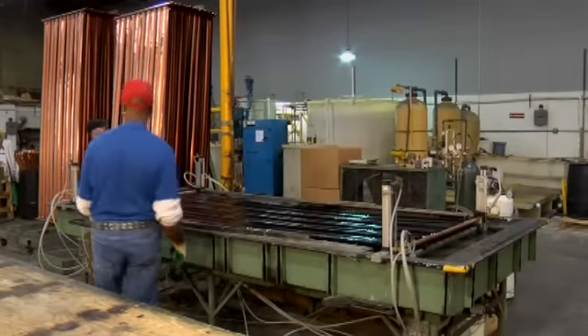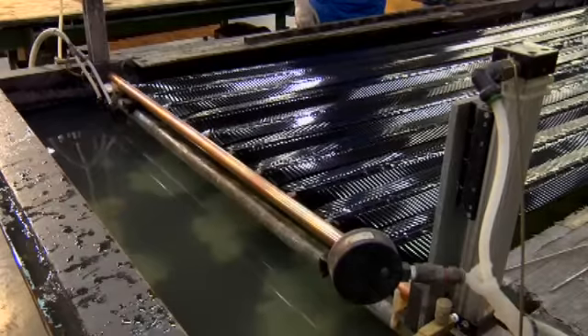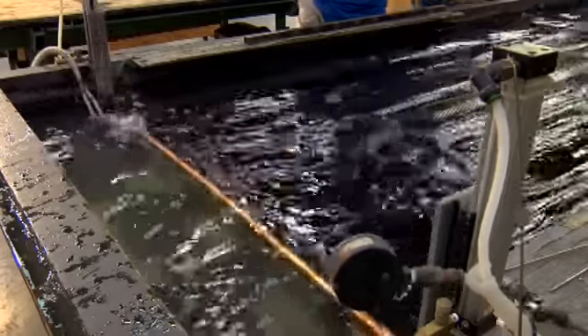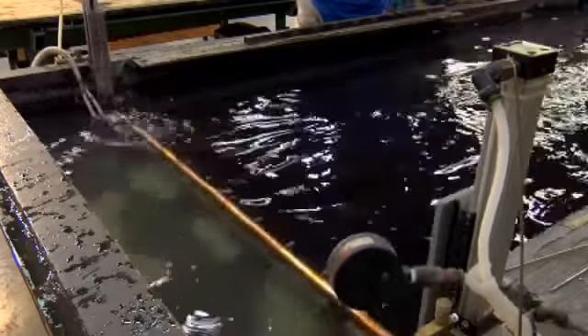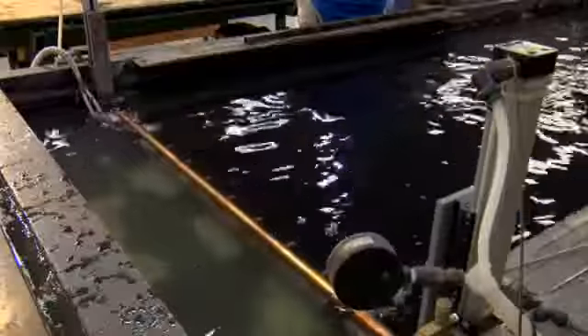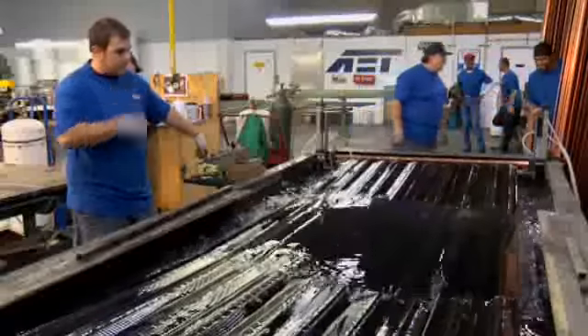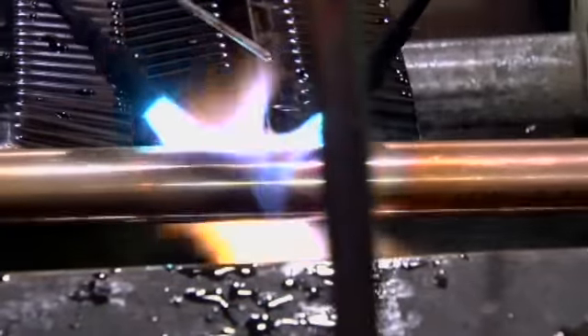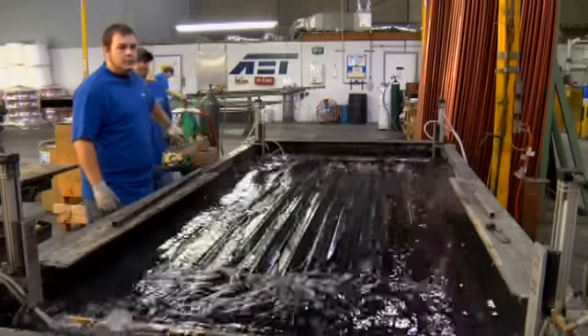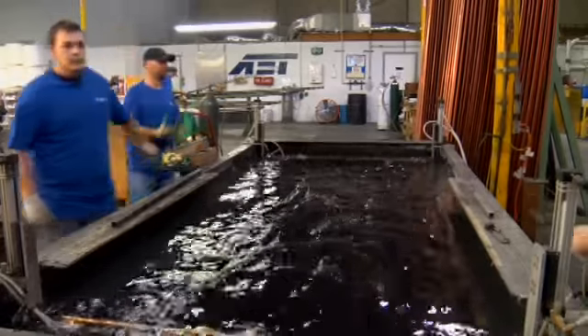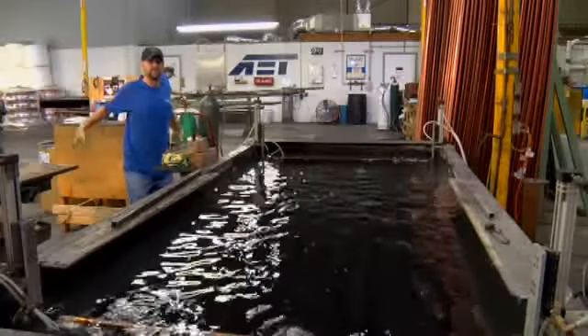The plate is placed on the rack, the headers are clamped, and then it's immersed in water under pressure. The air valves are opened to release air inside the absorber while it's checked for leaks. Should air bubbles be present, the absorber is raised out of the water and any leaks are repaired. Again, the absorber is immersed in the water and goes through the same checking process to ensure the integrity of the absorber plate.